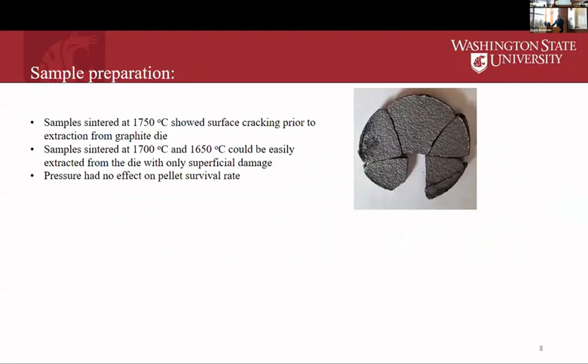After sintering, we found that even at 1750 degrees C, we had a lot of problems extracting pellets. It seemed that at 1750 degrees C, the yttrium oxide would eat through the graphite foil and become welded to the inside of the die. Because it was welded to the inside of the die, during heating and cooling it would end up cracking the pellet, and when extracted from the die, you got this — a destroyed pellet.